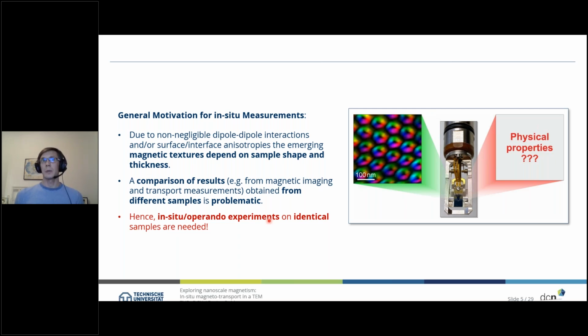So this seems to be problematic, since for magneto-transport measurement, you need quite large samples to really contact them. And in a TEM, as you all know, we need quite thin samples at a very small area. So that led us to the idea to really do such experiments on the identical sample and to come up with an in situ magneto-transport setup in the TEM. So we want to combine here